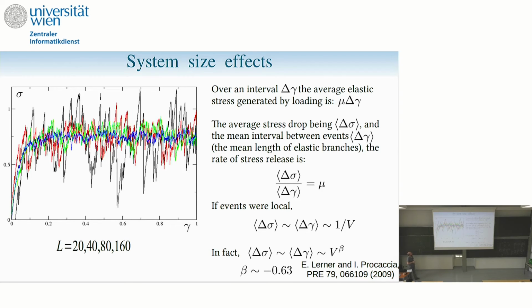Now, over a strain delta gamma, on average, you increase the stress by the modulus times delta gamma. So the rate per strain, the increase of stress per unit of strain, is mu. That's what the modulus is. Now, here we release the stress by drops. Suppose that I denote delta sigma the average stress drop, and delta gamma the average interval between drops. So the rate of stress release is essentially delta sigma by delta gamma, and if I'm in steady state, I'm only looking at steady state, the elastic increase of stress has to be equal to the plastic release of stress, and it tells me that the stress drops and the intervals between drops have to be related.